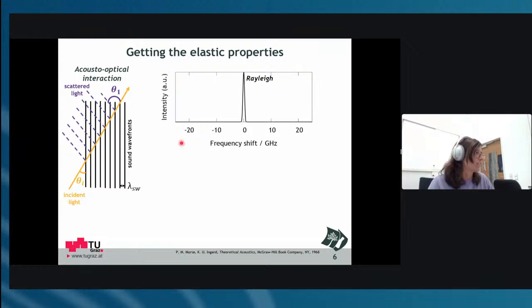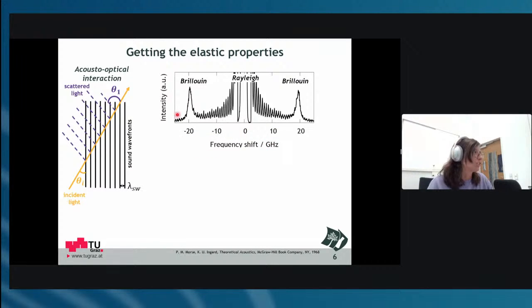So you always see the intensity over the frequency shift, and the frequency shift in Brillouin is always in gigahertz. And then you can zoom in, and then you see your Brillouin doublet. So what we do now is you can do some smoothing of the data, and then do a Lorentzian fitting or DHO fitting to get the position of your peak. So this is the frequency shift, and this is roughly at 20 gigahertz. And you can also determine the line width of your peak.